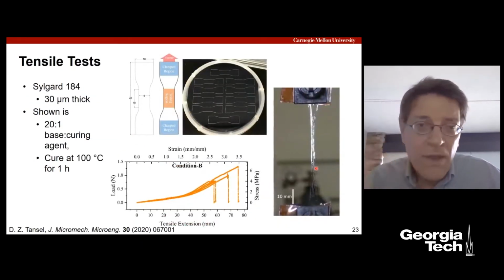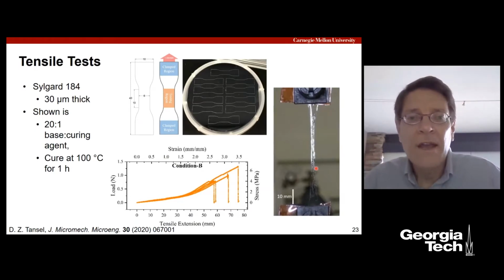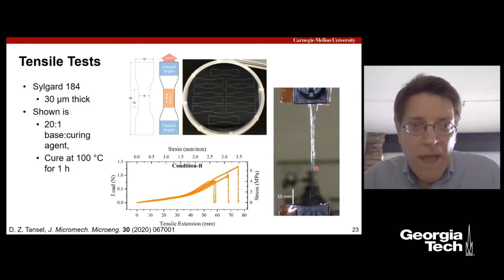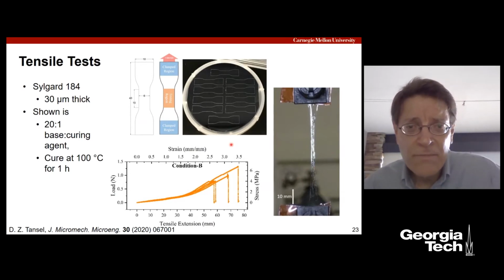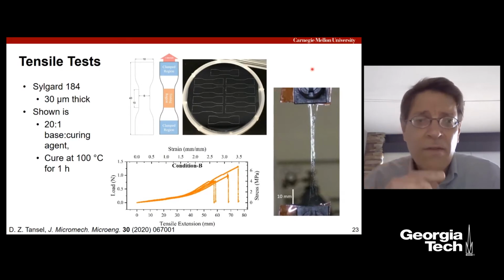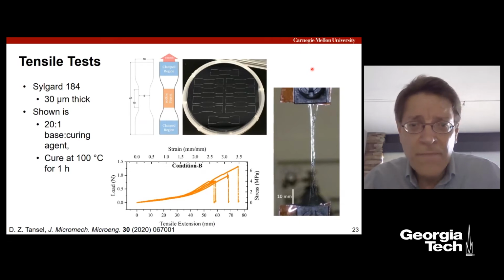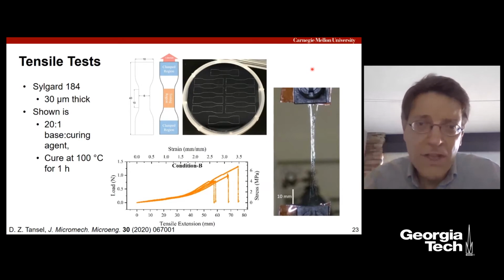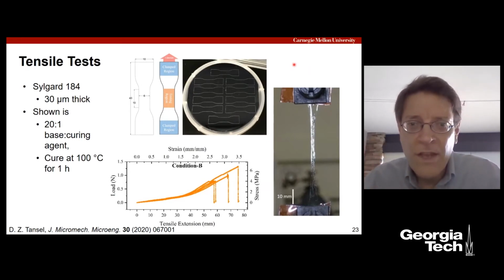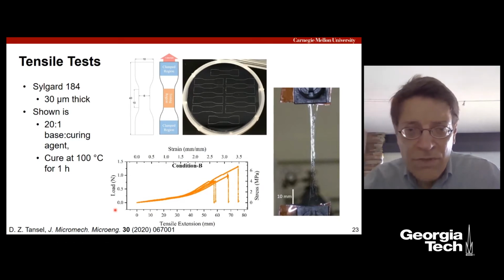So then, we embarked on, okay, well, we could anneal this in high temperature. What happens to the material properties at high temperature? And we looked in the literature and really couldn't find anything definitive about that, except for people to say don't do it. So we embarked on this. We spin cast a bunch of wafers with various types of PDMS, and then used a so-called Cricut cutter. This is a commercial machine. In this case, we cut out dog bone shapes, ASME type of tensile structures, and put these in an Instron machine and pulled, as you can see on the right, to get load extension curves, or so-called stress strain curves.